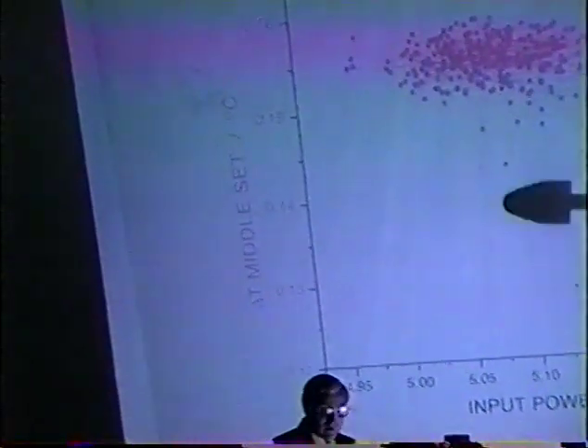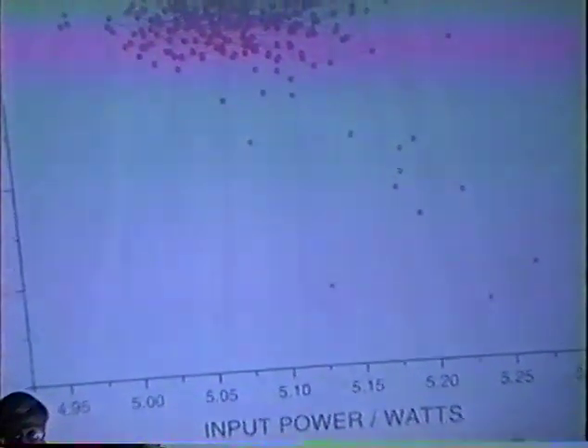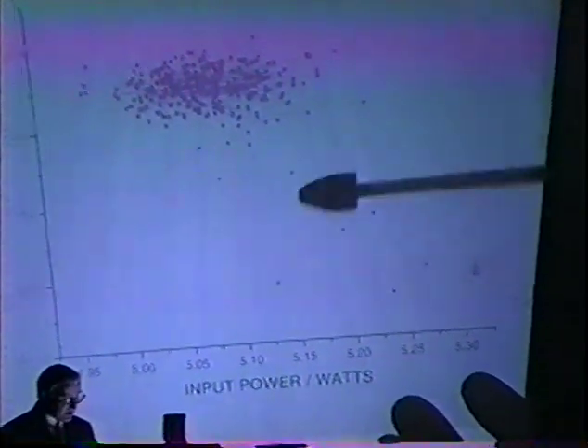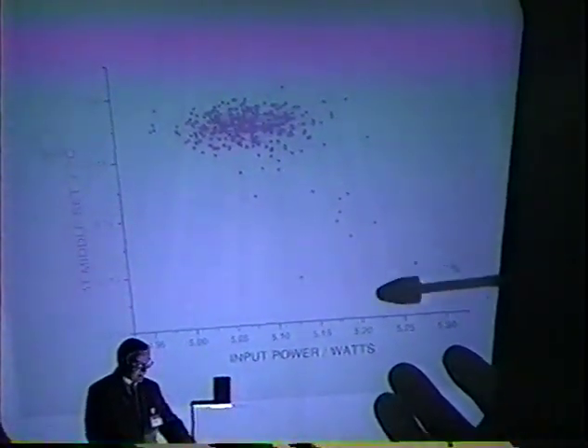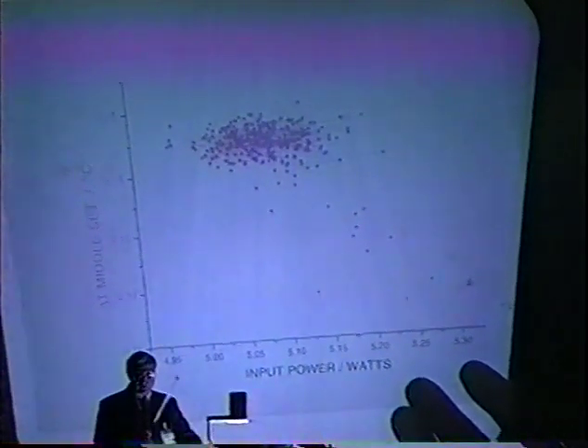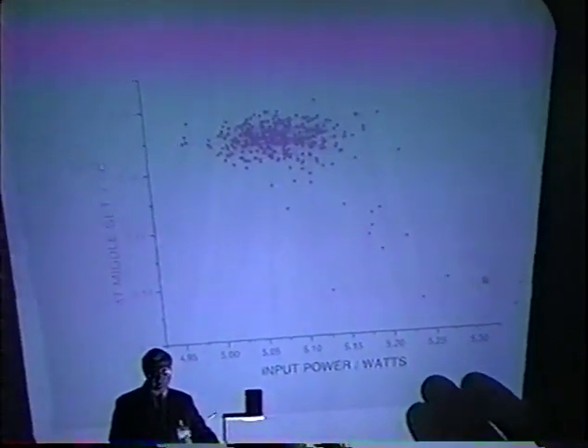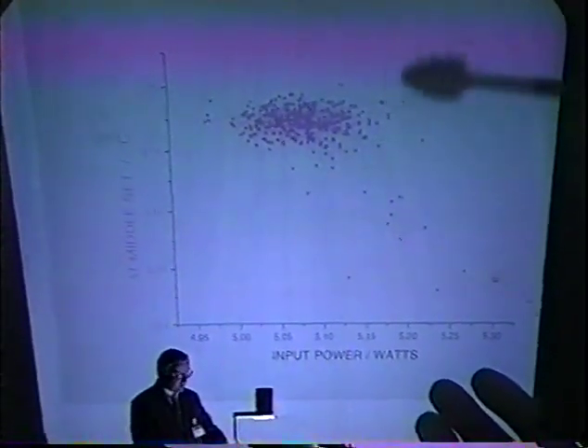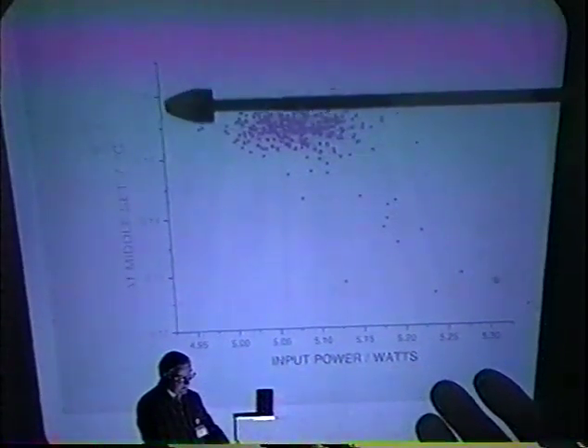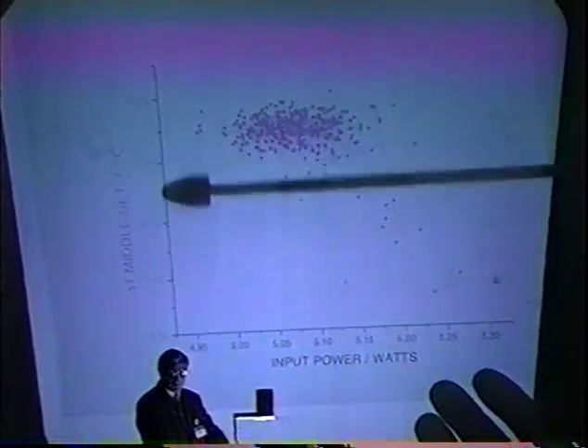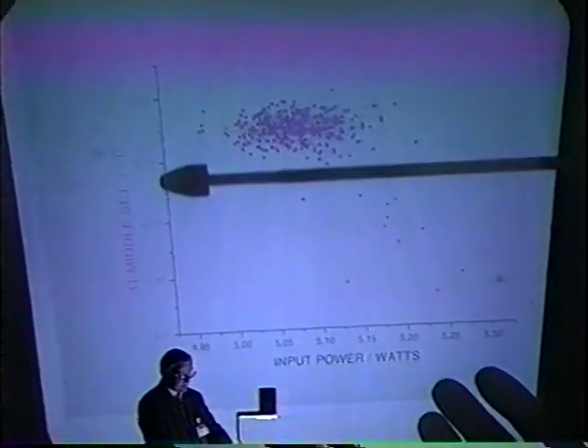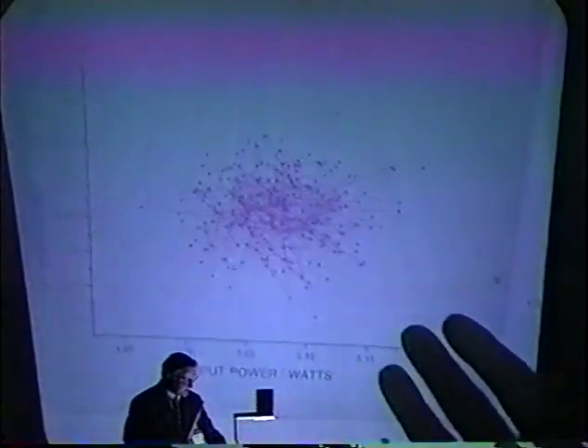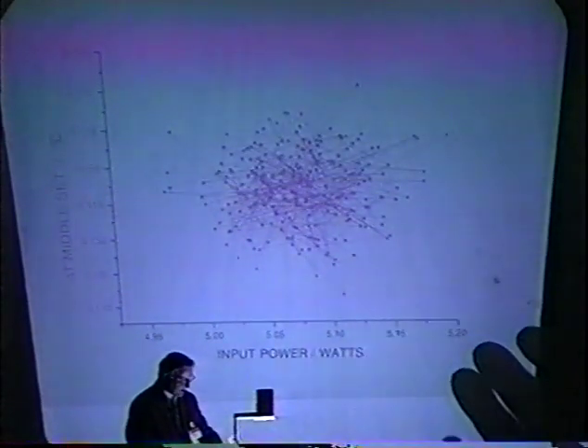This being the points that you saw in the curved portion, the unsteady state points. So the unsteady state points, then, this is a steady state calorimeter. As I said, we want to get rid of all the time dependency of the unsteady state in order to make a steady state measurement. In doing that, you can eliminate these points which contribute to the known determinant error. And in doing that, you then arrive at a spread that looks like this for a given temperature and given power.